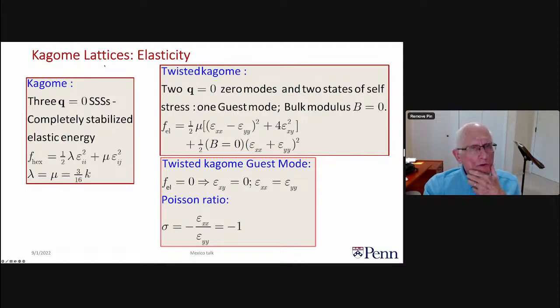Maxwell lattices have some exotic elasticity. So the Kagome lattice has all of the elastic constants that a standard isotropic elastic medium has. The epsilon ij are the linearized strains. And here we take, for the nearest neighbor bonds, lambda equals mu is 3/16 k.